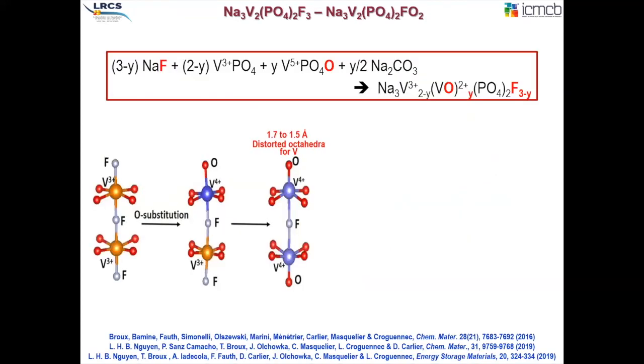Second fascinating thing is about the fact that we can somehow tune the electrochemical properties by playing with the fluorine over oxygen ratio in this compound. I mentioned already that the orthorhombic phase of F3 is properly described, but with different synthesis conditions, playing with the oxidation states of the vanadium precursors, for instance, we can obtain oxygen-substituted fluorinated compounds with a whole range of Y values.